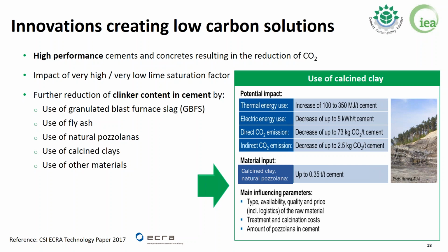This could be a new solution having a widespread use in the future. And then for each of these low carbon solutions within the roadmap, there is a detailed assessment of their impact, the quantity of substitution, the maximum quantity of substitution that is allowed, and which are the influencing parameters. You see here an example specific on calcined clay. As said, due to the drying process of raw clay, the use of calcined clay will require higher thermal energy used per ton of cement, but at the same time there will be a decrease in terms of electric energy used. So overall, the use of calcined clay allows for a decrease of direct CO2 emissions, approximately 73 kilograms of CO2 per ton of cement, and also a decrease of indirect CO2 emissions, 2.5 kilograms of CO2 per ton of cement.